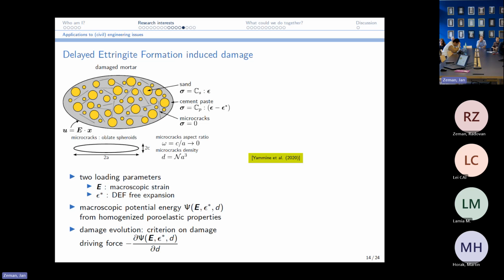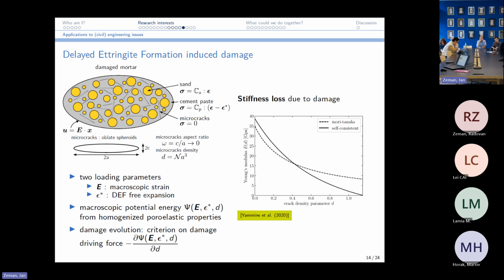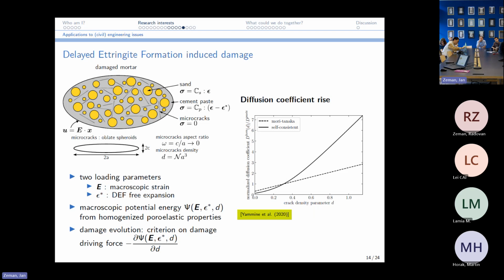And then we would propagate damage or increase the microcrack density based on the driving force, which is the derivative of this potential energy with respect to this density of microcracks. So independent of this damage criterion here, what we can see from homogenization is that as you increase the crack density parameter, you will reduce the Young modulus, and similarly for all the coupling terms in the poroelastic formulation. Then the diffusion coefficient will increase in turn, which will accelerate the leaching and will in turn increase the free expansion.